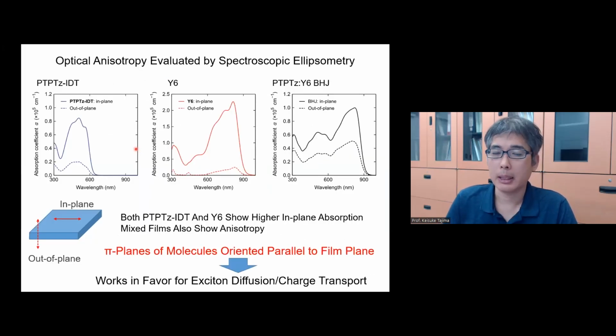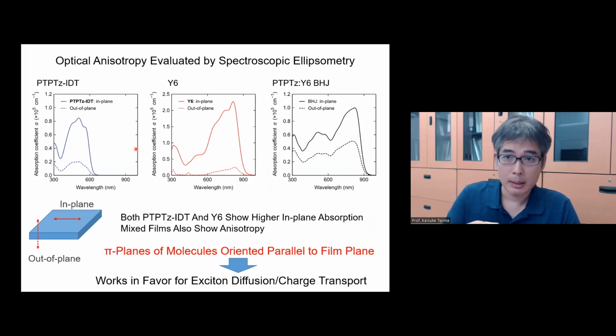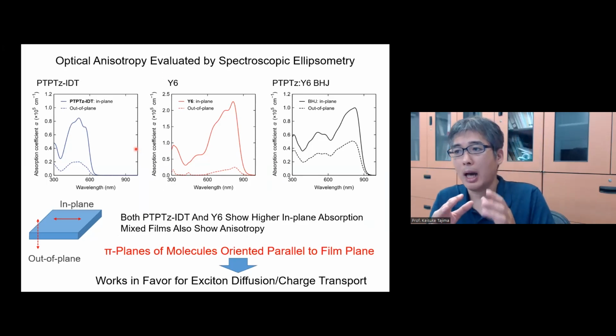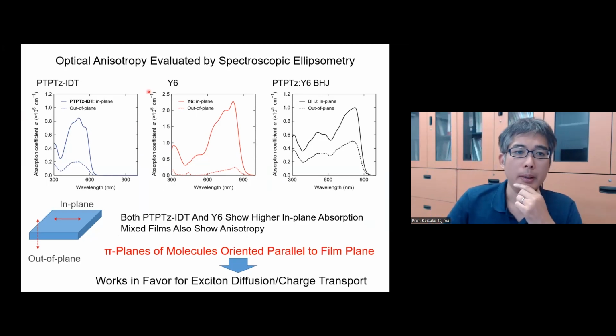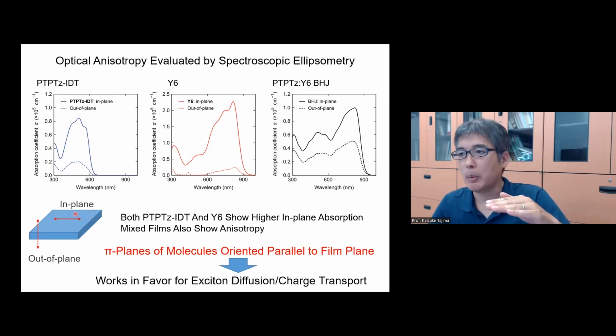So what we rely on is optical ellipsometry, like in the previous case. This is good because you don't need to have the crystalline material, and the average molecular orientation can be estimated by this optical anisotropy. So the polymer film shows this absorption coefficient in the in-plane and the out-of-plane. This is the in-plane, so parallel to the substrate. Out-of-plane is vertical. So out-of-plane is much smaller than in-plane. That means that the transition dipole moment, or say the polymer chain, aligns in-plane in this polymer film.